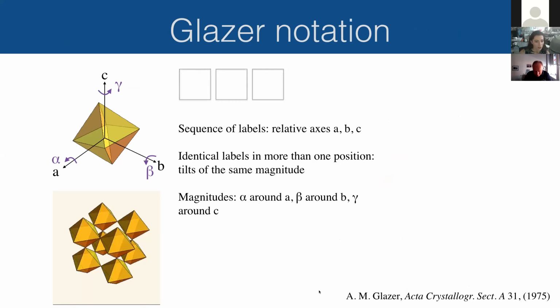So Glazer notation. You have to visualize just an octahedron. Now I don't show the oxygens on the corners, but in principle they are there. And you allow this octahedron to rotate without changing its shape. So the bonds are somehow rigid. And then you look at the 3 crystallographic axes, A, B, C, and each one of these axes will receive a label, which will go here, here, and here. So A, B, and C. So which label lands first, second, or third tells you A, B, or C. And then if you have a repeated letter, so for example, AA, what it means is that the magnitude of the octahedral rotation around the A axis is equivalent to the one around the B axis.